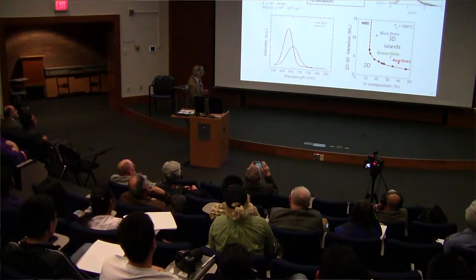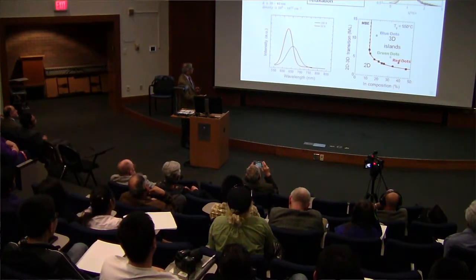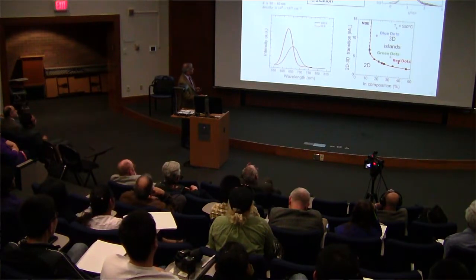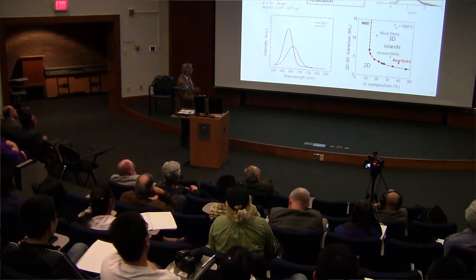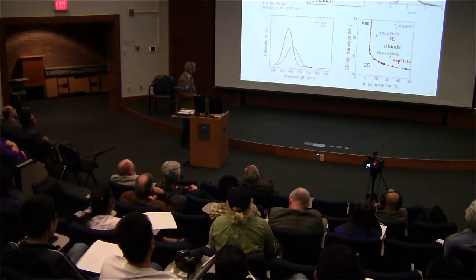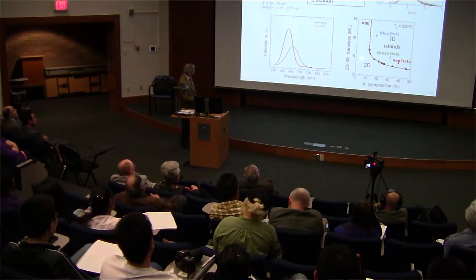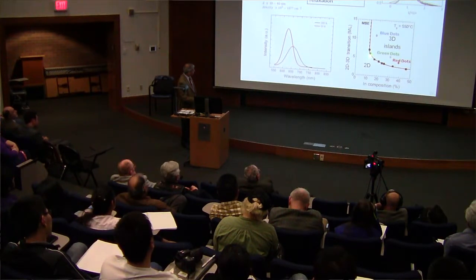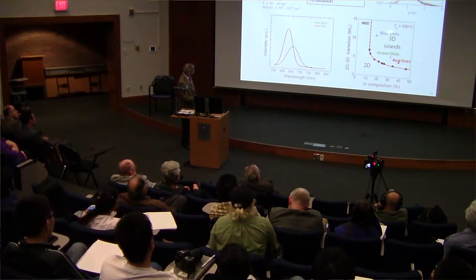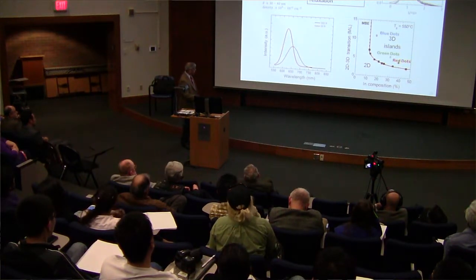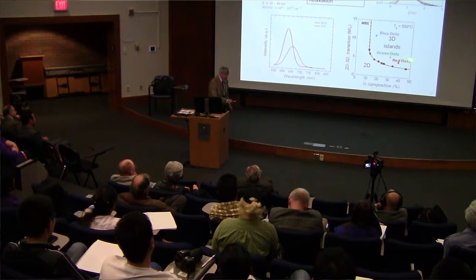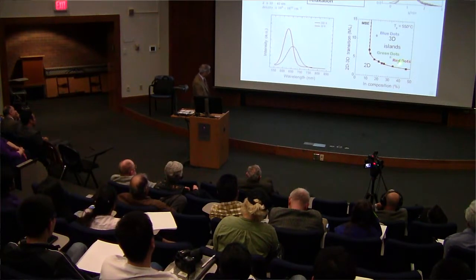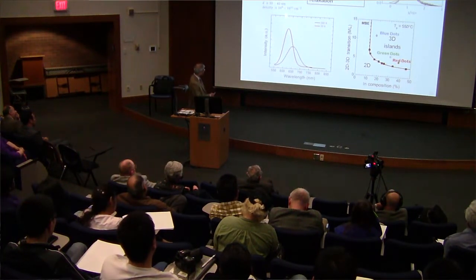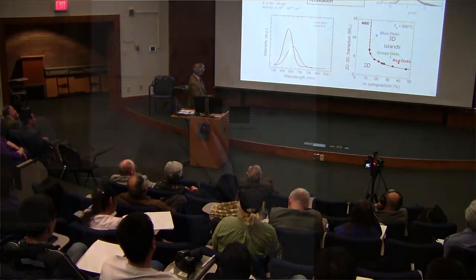As we increase the temperature of the substrate, i, which is one less than the number of atoms that make up a dot, increases, and so it's kinetically driven. This is the phase diagram, the transition from 2D to 3D, and so you can see we are growing red dots and green dots and blue dots. By the way, we were the first ones to show any red emission with the nitrides, both with the nanowires and with the quantum dots. And here you can see the emission in the red at room temperature.